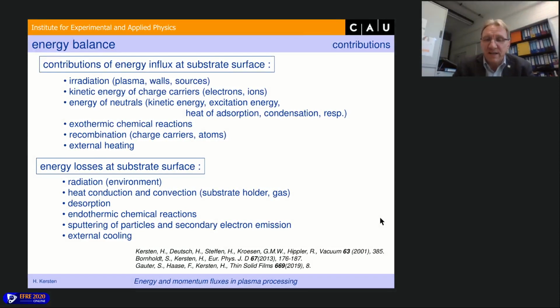Okay, as I already mentioned, this energy influx, or the power which is deposited at the surface, or the power balance, is influenced by different contributions. For instance, you have gain and you have loss processes at the surface. Gain processes might be irradiation by the plasma itself, depending on the energy of the plasma, by surrounding walls, which might be heated, or even by sources. For instance, if you have an electron beam evaporation, then you have a very hot crucible, which is a heat source for your substrate. There might be kinetic energy of the charge carriers, of the electrons and ions. This contribution depends on the bias voltage, of course. For a positive bias voltage, you will attract more electrons, and for a negative, you will attract more ions.